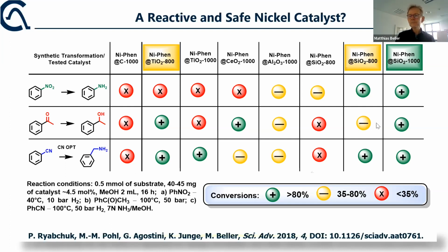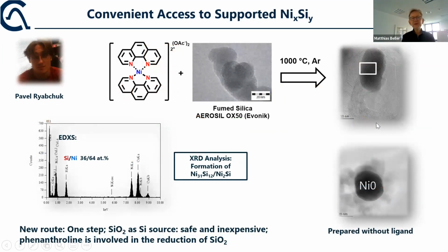The interesting thing about this catalytic material was discovered when we looked more carefully at the material by various analytical techniques. While classical nickel nanoparticles on carbon and other materials form nickel zero metal nanoparticles with varying sizes, this specific material behaved somehow differently. In fact, if you look at the surface of the catalyst material, you observe different phases of nickel silicides on the surface. This was very surprising for us because we didn't expect the formation of nickel silicides to take place in this reaction.